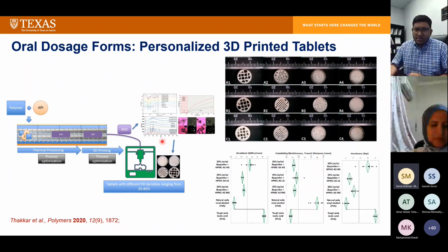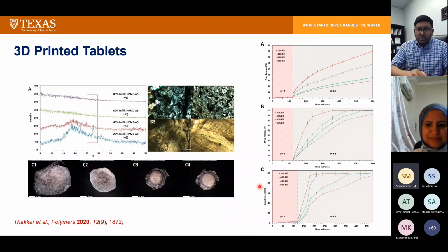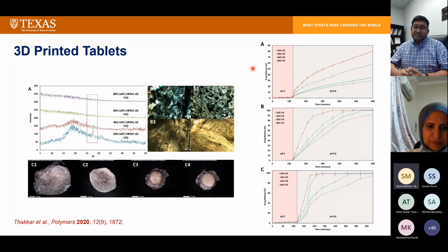And then after producing the filaments, we did some comparative mechanochemical characterization, and what we found is that our produced filaments, in terms of their gradient value, flexibility, and hardness, were between the upper limit and the lower limit. So we actually used two different reference materials taken from the market basically, and we used them as soft and hard references. And what we found is that our produced filaments all fell between these two ranges, which seems to be printable, right?